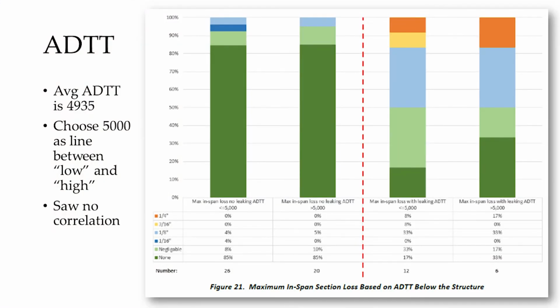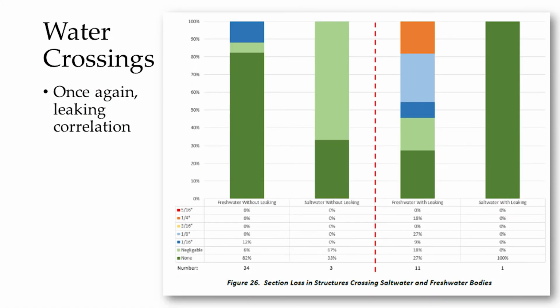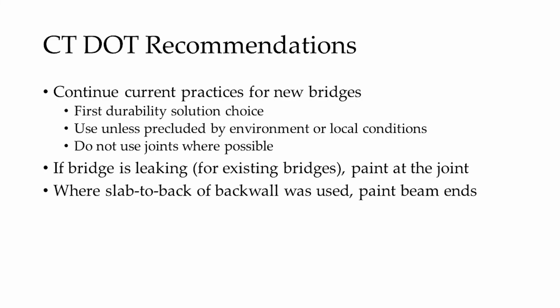Of course, those are perhaps much higher traffic than you might get in urban Connecticut. Regardless, there are 26 bridges under 5,000, 20 over 5,000 a day, and they didn't see a significant difference in traffic. But they did notice on the bridges on the right where you're leaking, you do have that problem. Water crossings, again, it didn't seem to make a significant difference, except that there was a correlation with the bridges that leak.